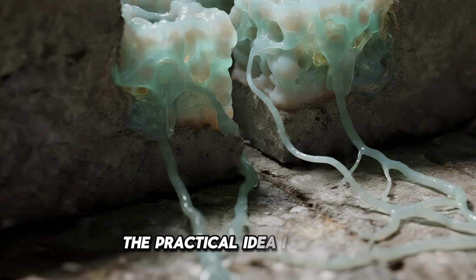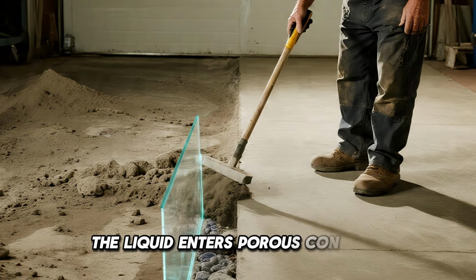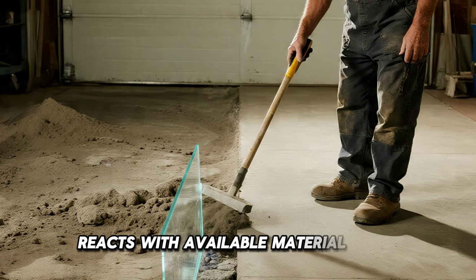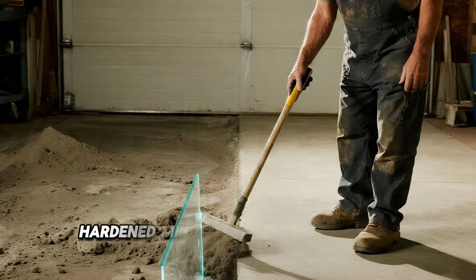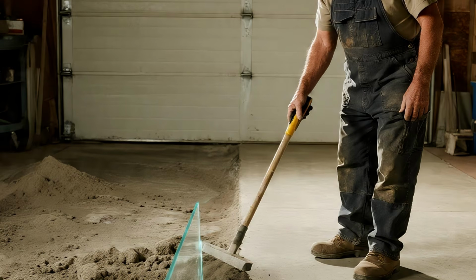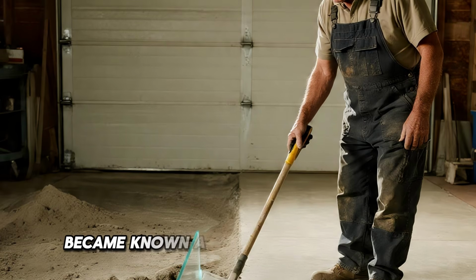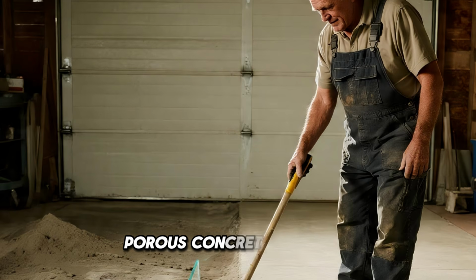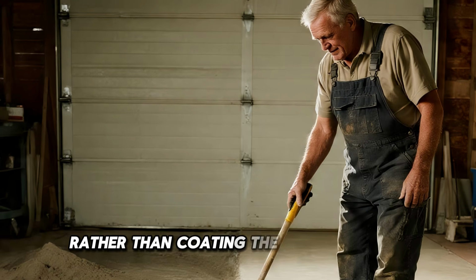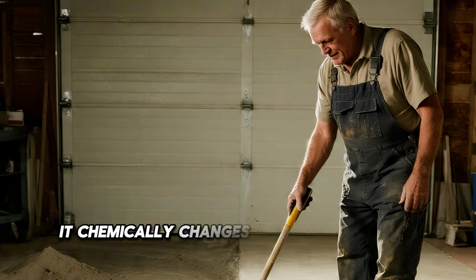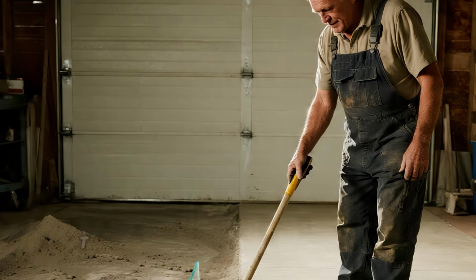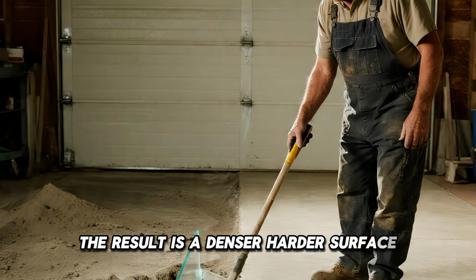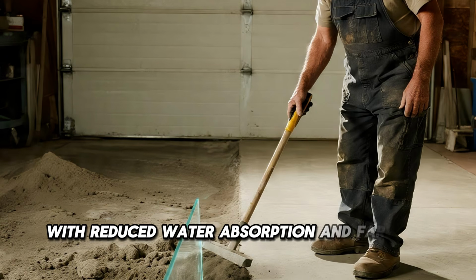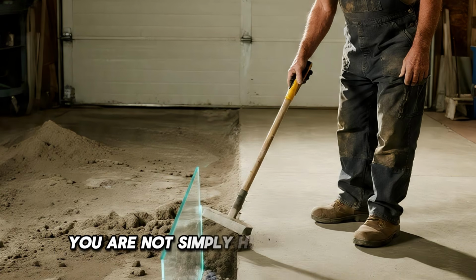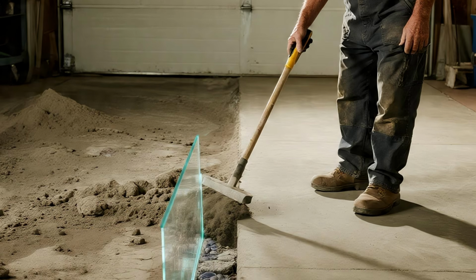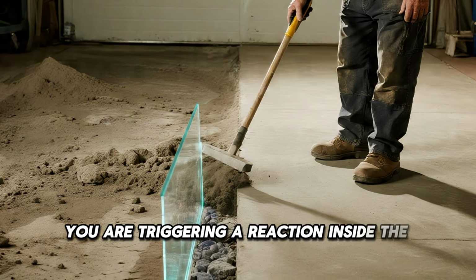The practical idea is simple. The liquid enters porous concrete, reacts with available material inside, and creates additional hardened mineral deposits within the capillaries. That is why sodium silicate became known as a treatment for dusty, porous concrete surfaces. Rather than coating the slab like paint, it chemically changes material inside the concrete. The result is a denser, harder surface with reduced water absorption and far less dusting. You are not simply hiding the weakness beneath another layer. You are triggering a reaction inside the slab itself.